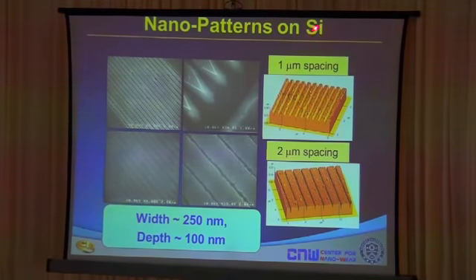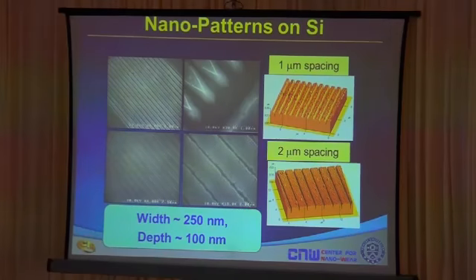This is a silicon surface with 1 micrometer spacing, width about 250 nanometers, depth about 100 nanometers. Obviously, you can make this kind of pattern using photolithography, but photolithography will require several steps, and you have to make a mask. And once you make a mask, you cannot change the pattern. But if you use this process, you can simply program your AFM tip to whatever pattern you like, so you're very flexible in terms of the kind of patterns that you can make. So we propose this method as a flexible way of making a small number of parts with surface patterns.